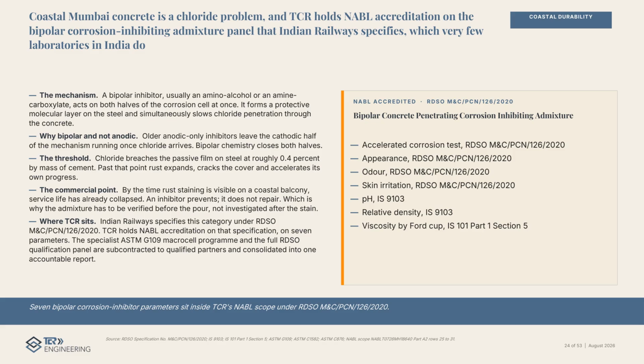Chloride breaches the passive film on steel at about 0.4% by mass of cement. And past that point, the rust expands, cracks the cover, and accelerates itself. Indian Railways specifies this category under RDSO specification 126 of 2020. TCR holds NABL accreditation on 7 parameters of that specification.